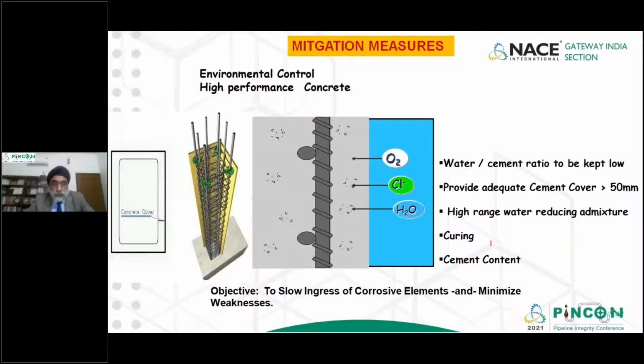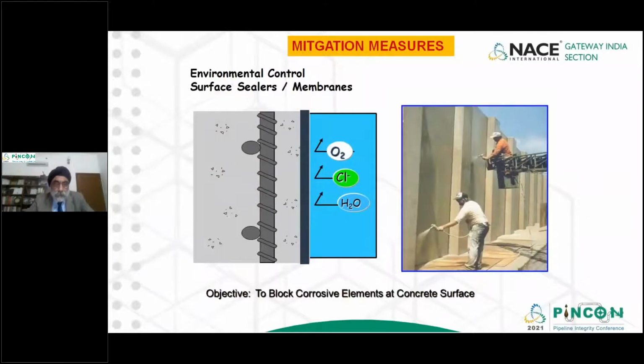The objective of this strategy is to slow ingress of corrosive elements into the rebar. Now we can reduce this by about 10 or 15 years, but eventually through the concrete, these corrosive elements will hit the rebar and cause corrosion. So this is a mid-term strategy. It's not a long-term strategy.